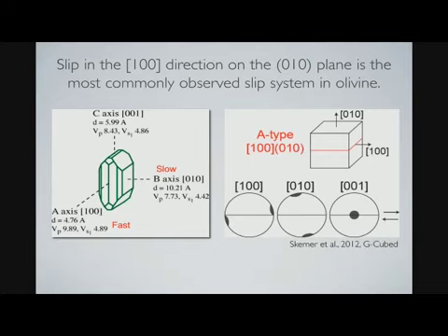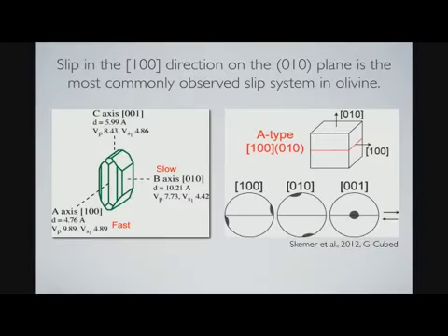And the way that we figure this out in looking at natural samples is looking at the pole figure, which is plotted at the bottom here. So this is an olivine pole figure showing this easy slip system. This is just a schematic, showing a maximum approximately aligned up with the shear direction, so that is the slip direction. And that which is normal to the shear direction is the slip plane. And then the [001] axis, or the C-axis, is not dominant in this slip system. So when olivine is deforming by a dislocation mechanism, it results in an alignment because it is dominantly slipping on a slip system such as this one, and that is what is giving rise to seismic anisotropy in the mantle.